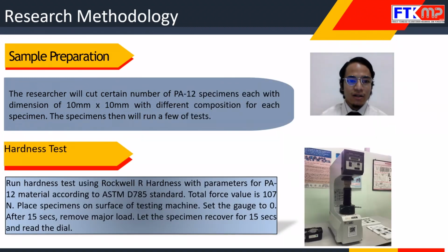The next step is sample preparation. For my sample preparation, I will cut the specimen of PA12 with a dimension of 10 mm by 10 mm area, with a different composition for each specimen. After that, I will run several tests. The first one is the hardness test. For the hardness test, we use the Rockwell R hardness with the parameters for PA12 specifically. This is according to the ASTM standard.